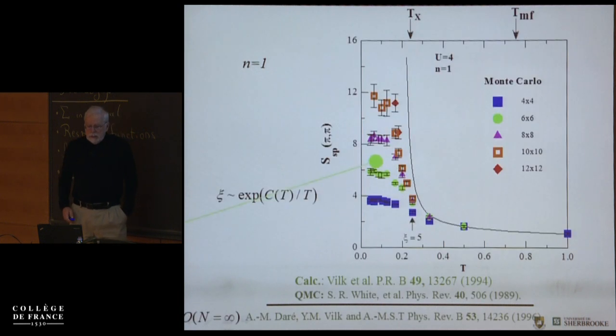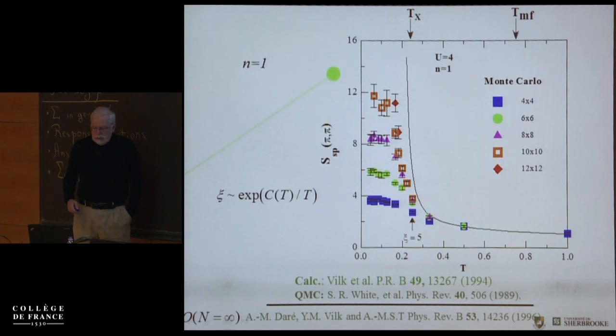So let's look at something a little stricter. You look at half filling, n equals 1. This is again the structure factor, but at pi, that's the one that is going to diverge, and that's as a function of temperature. If I was doing RPA, I would get a mean field transition temperature here at 0.75 roughly, in units of hopping all the time. Instead, you see what I get in TPSC is this solid line here. So it starts to go up at a much smaller temperature. So that's the Kanamori-Brueckner effect.